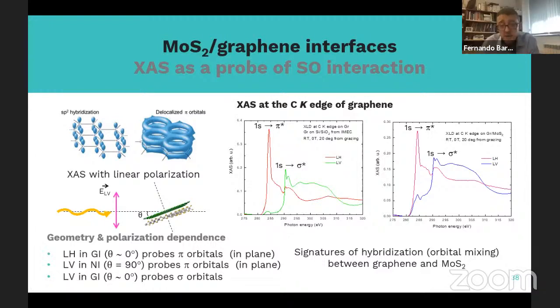Yeah, but that is true indeed. It's not an easy experiment. So in fact, what we do to make sure that we have a clean carbon is to anneal in situ the sample, just to make sure we have clean interfaces, or try to remove the carbon that is adsorbed on top of the sample. But so you are still trying to understand, you don't have a mechanism. No, yet. Or how does the molybdenum sulfide act on graphene?